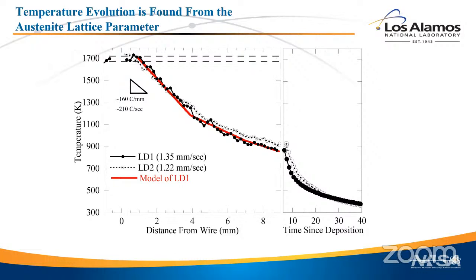So now, because we've slowed down the system and because we turned it into a quasi-steady state, now we can pull out data on relative time and length scales. So you can look, for instance, as a function of distance from the wire, distance from the weld pool if you want, the temperature. So the dotted lines represent, depending exactly on the chemistry, the melt point of 304L stainless steel. And this isn't forced. We actually, by measuring the lattice parameter and knowing the thermal expansion of austenite, we calculate the temperature. It comes right at, it solidifies at the melt point. That's what it should do.